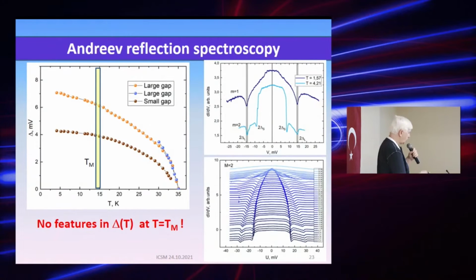And this picture is actually our goal. Again, with a much higher precision than from ARPES measurements, we can say that nothing happens with the amplitude of the order parameter at the temperature where the magnetic transition occurs. So at this point, we can say that the magnetism and superconductivity are decoupled from each other.